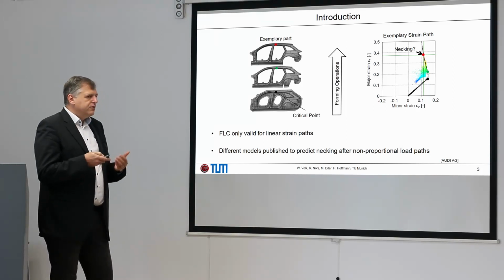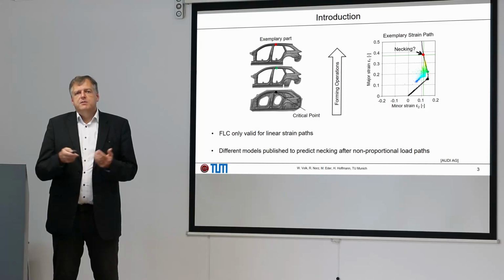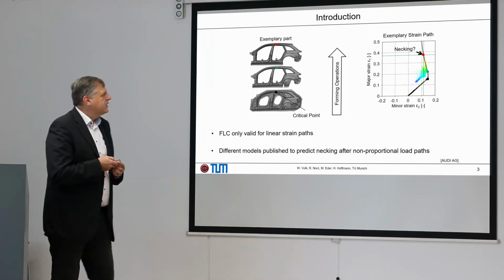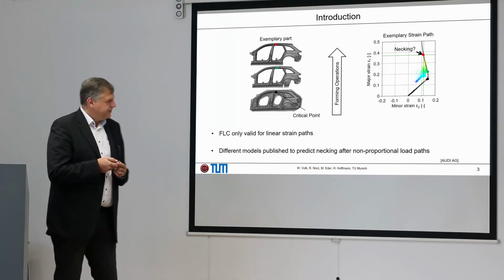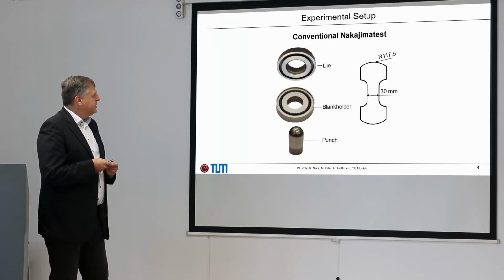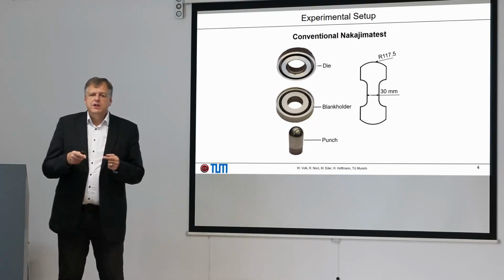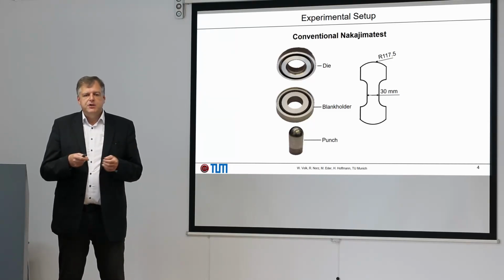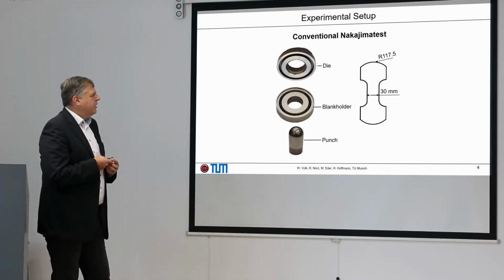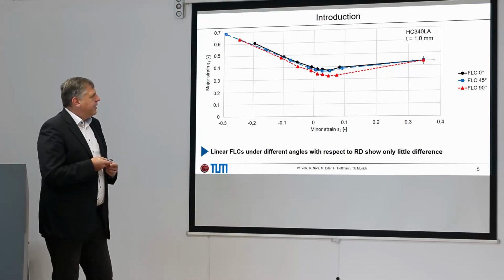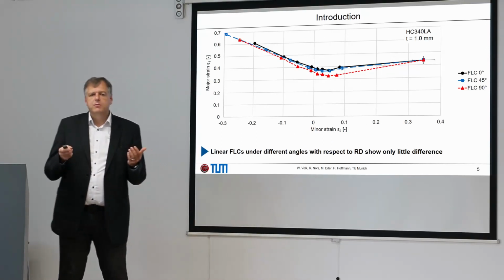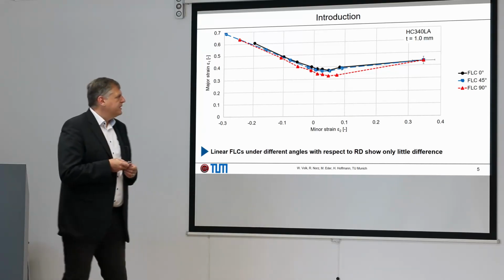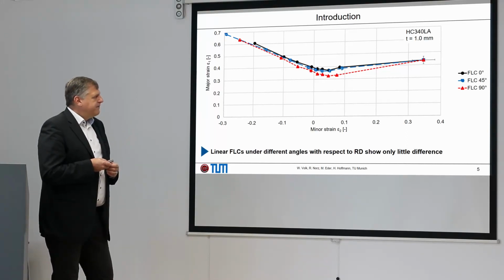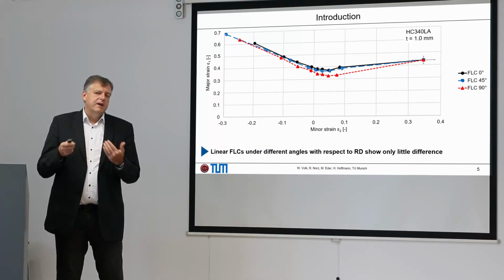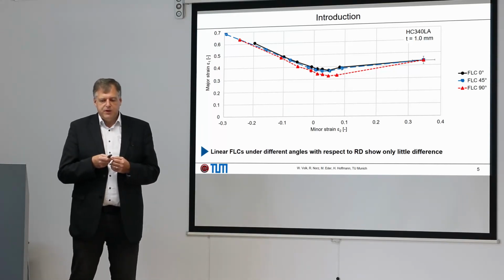Therefore, it's necessary to do some tests, and especially for the FLC, we start with the usual test equipment, this Nakajima test. So we have used the conventional Nakajima test with the die, blank holder, the spherical punch, and you know that it's possible to change the ratio of minor and major strain just by changing the size of the specimens. Here, for our material, with this absolutely common steel material, a HC340LA steel, we know that we have some slight differences also for the FLC, the linear FLC, with respect to the rolling directions.